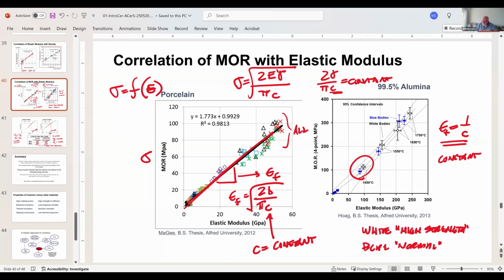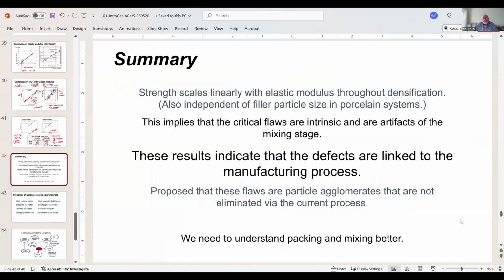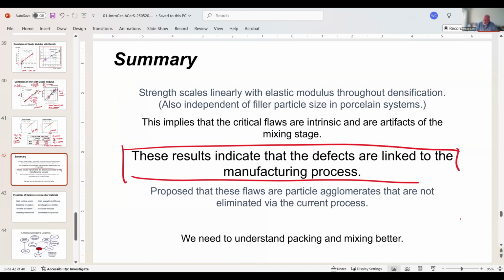Okay. Now they're processed the same way. They're different compositions, slightly different compositions. And if you come out here, you'll see why. Here's my blue strength. Here's my white strength. So the white strength is slightly stronger than the blue strength by maybe 20 megapascals. Not a big difference. But the flaw populations for these two materials processed in the same plant, I'm not going to tell you where, they have the same flaw populations, right? So what does that mean? That means that manufacturing defects are linked to the manufacturing process.